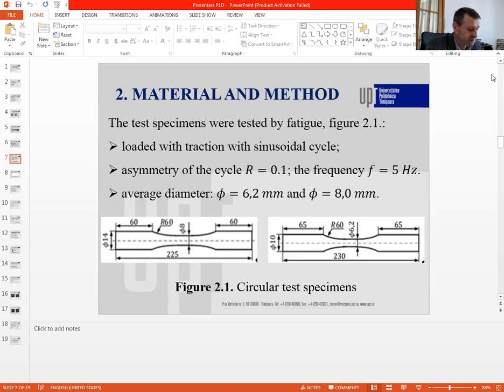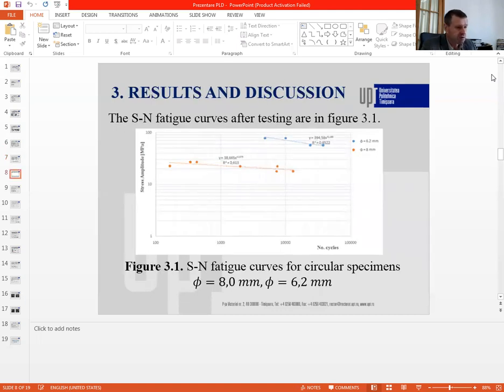The first set of tests consisted of specimens obtained by casting with an average diameter of 6.2 millimeters, and the second set of tests consisted of specimens obtained by casting and processed by cutting with an average diameter of 8.0 millimeters. A total of 7 specimens for each set were tested.